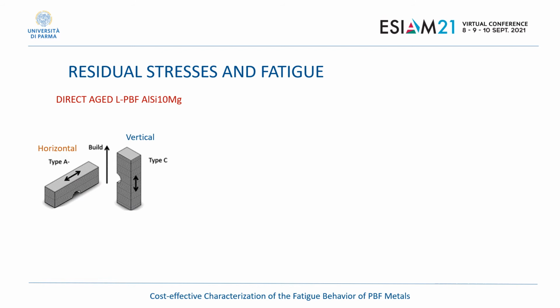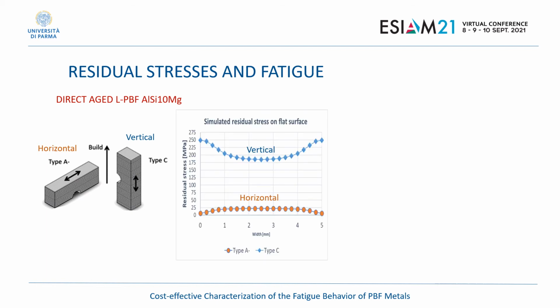We investigated the role of residual stresses in fatigue. We selected an aluminum alloy that we treated by a direct aging low temperature heat treatment. In this way, we expected to have a material with residual stresses still present in it. We prepared the specimens oriented in the horizontal and in the vertical directions, and we determined by simulation the residual stresses in the specimens. We found that the vertical specimen is characterized by very large tensile residual stresses, while the horizontal specimens have a negligible level of residual stresses.